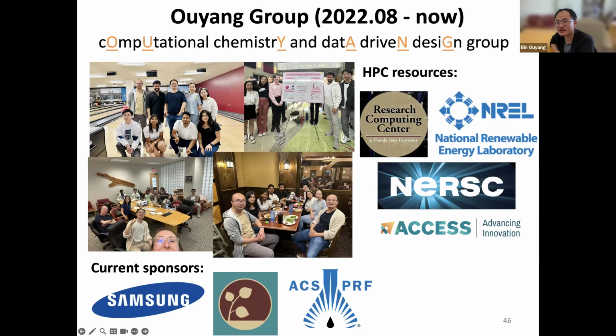I see. That's a very good question, and maybe I can provide two pieces of information. First of all, we benefit from the fact that battery people don't like elements with strong correlation effects, because heavy elements lower the energy density of battery materials. So typically we just deal with 3d elements and sometimes a little bit of 4d elements. In that case, hopefully there is less strong correlation. From my knowledge, and I'm totally not an expert in that field, we never use, for instance, the f-block elements.